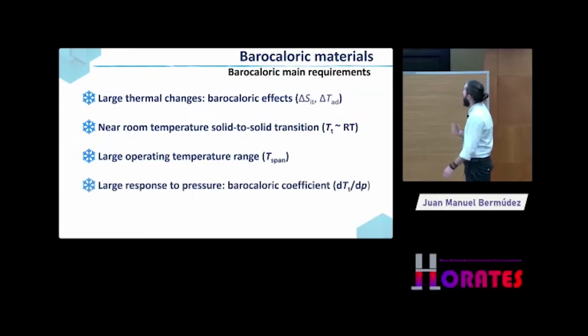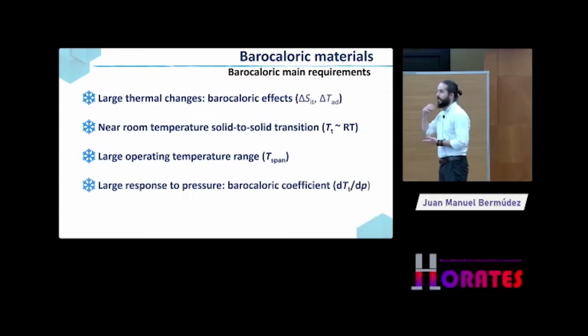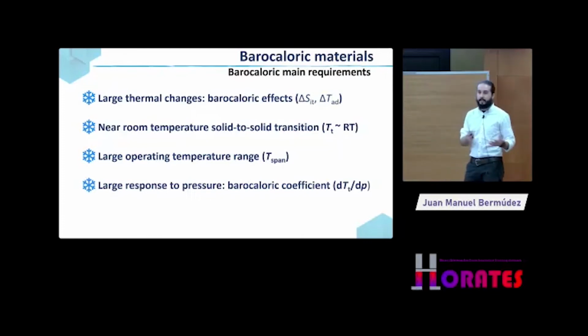Then it has to have a very large response towards pressure, meaning that the less pressure that you need to apply in order to induce a phase transition, the less energy you are going to need for the system to operate. So you increase the efficiency. This is a measure in terms of barocaloric coefficient, which is different from the barocaloric effects. And this coefficient can be measured as the transition temperature dependence with the pressure, meaning how much you can shift your transition temperature when you apply the pressure.